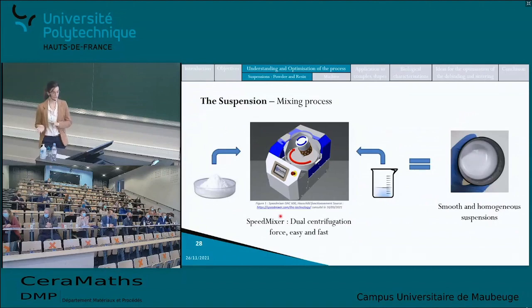So then I went to another technology, which is the speed mixer, that provides a dual centrifugation force, and that is easy and very fast. So I was able to obtain smooth and homogeneous suspension in less than 15 minutes, and also using only one container, so avoiding the transfer of the suspension and avoiding the mass loss during the process.